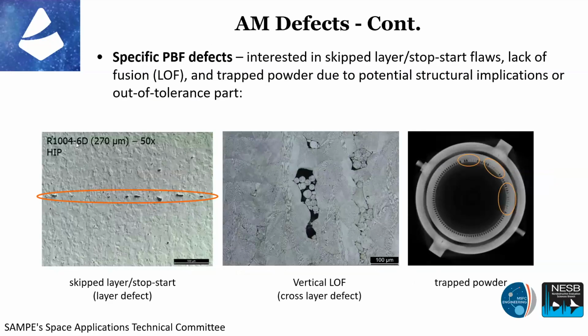Just a couple more. Some of these we've started to try and make intentionally so that we can pick them up in NDE, like skip layer, start-stop defects, vertical lack of fusion. And then probably the hardest one that we're working with right now are these trapped powders. And you can see the very slight grayscale differences, especially with some of the trapped powders, that can be very difficult to pick up with the current processes.